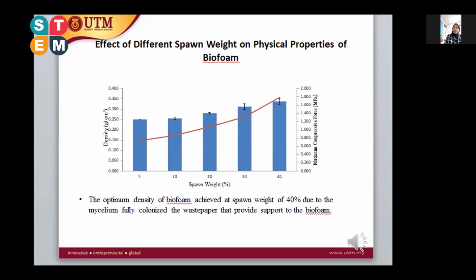Next factor studied for PO growth on waste paper was spawn weight. From the figure, it shows that the biofoam with 40% inoculum weight had more mycelium colonized on the waste paper after 10 days compared to other inoculum weights. The biofoam with spawn weight 40% had the highest compressive force, which is 1.788 MPa at 50% deformation. This is due to the mycelium that is fully colonized on the waste paper and provides support to the biofoam.